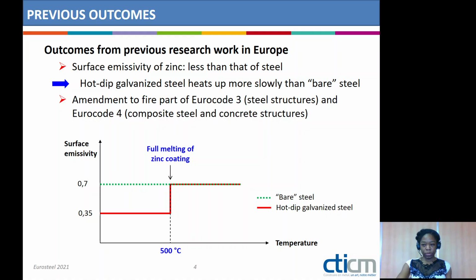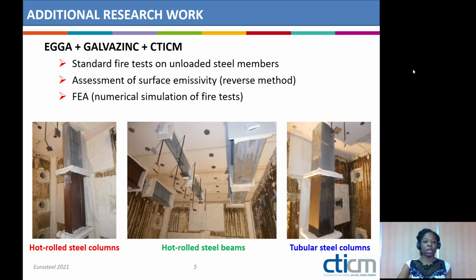In order to confirm and definitely validate this amendment, additional research work was carried out by EGGA, GALVAZINC, and CTICM in France. This additional research work consisted in carrying out standard fire tests on unloaded steel members. Once the tests were conducted, the results were used in a reverse method in order to assess the surface emissivity of the specimens. And also, finite element analysis was conducted in order to simulate the thermal behavior of the fire tested specimens. As you can see on the pictures, different types of specimens were fire tested.